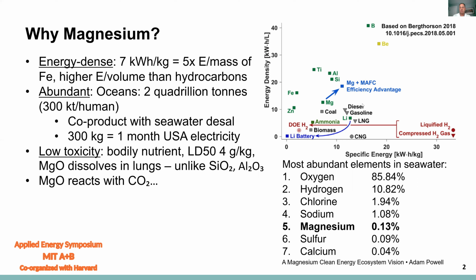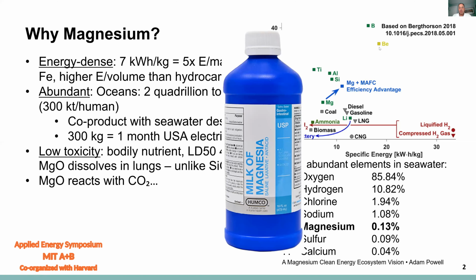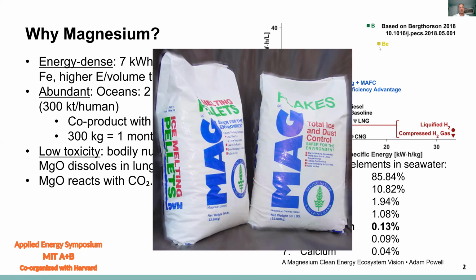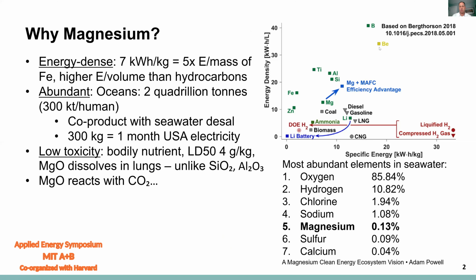Third, magnesium is not only non-toxic, it is a necessary bodily nutrient with LD50 in rats measured at 4 grams per kilogram. So for a human, that would be about a pound of magnesium oxide. In contrast, silica and alumina are much more toxic, with aluminum linked to Alzheimer's disease, as of course are boron and beryllium. And in contrast, we drink magnesium oxide for upset stomach, and we dump magnesium chloride onto our roads by the hundreds of tons to melt ice. It's good stuff. And MgO also reacts with CO2, but I'm getting ahead of myself.